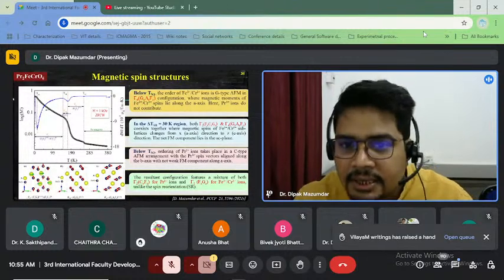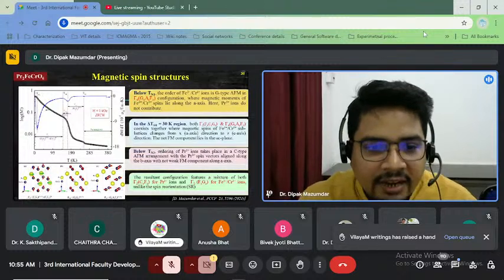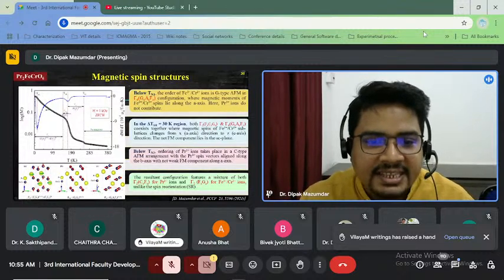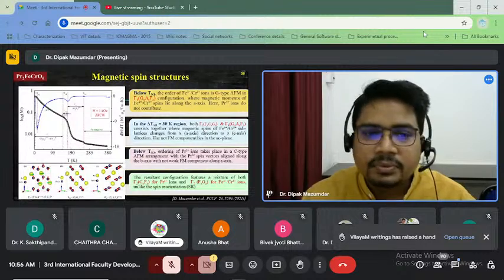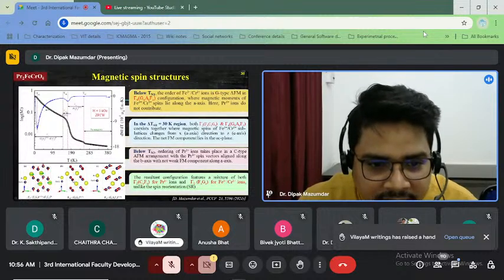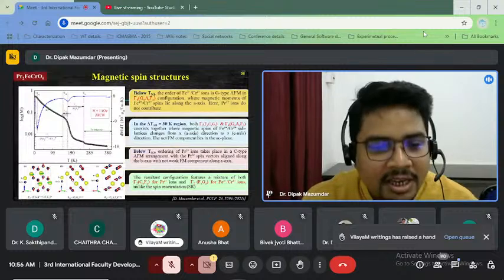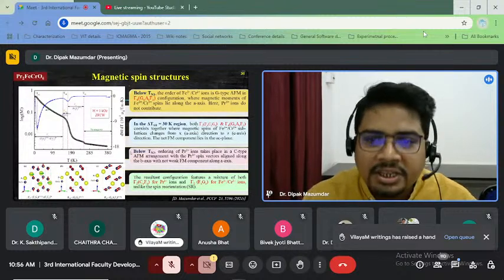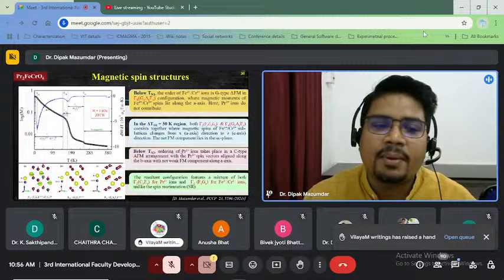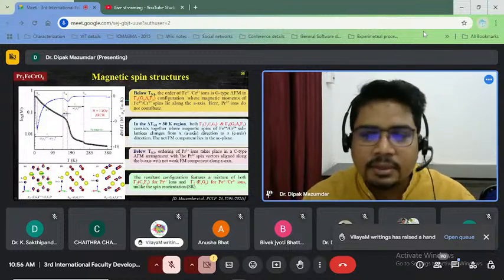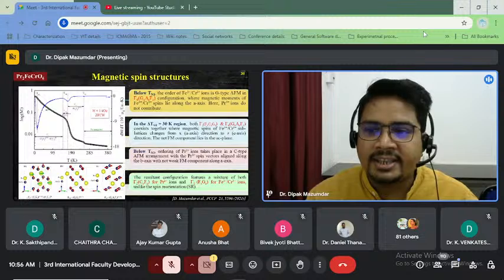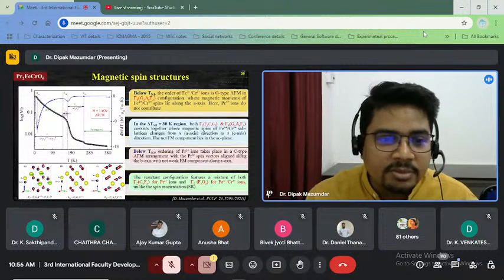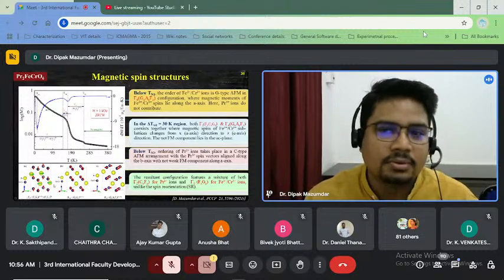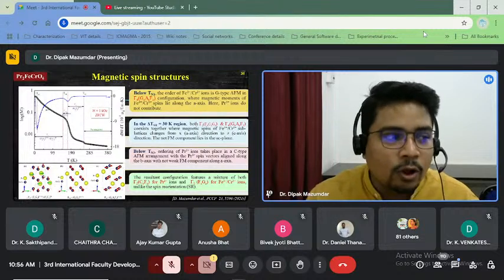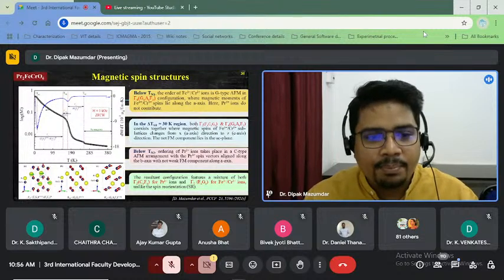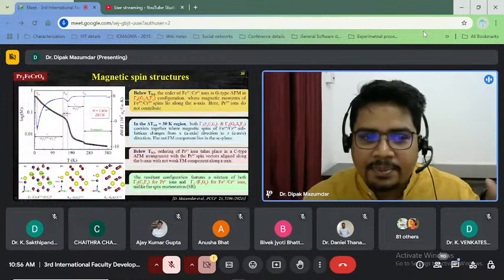So here you can see there is a net ferromagnetic component present in the AC plane. But all those, this is up, this is down. They are antiferromagnetically aligned, although. And below TN2, now the praseodymium ion will come into the picture, and praseodymium ions will arrange in a C-type arrangement. C-type arrangement is what? Up, up, down, down. So they are antiferromagnetically aligned, although in plane they are up, up, down, down, which is the signature of C-type arrangement.